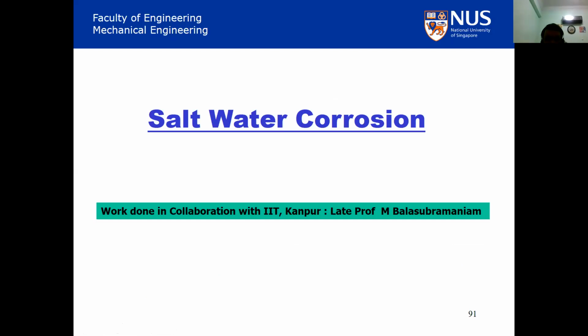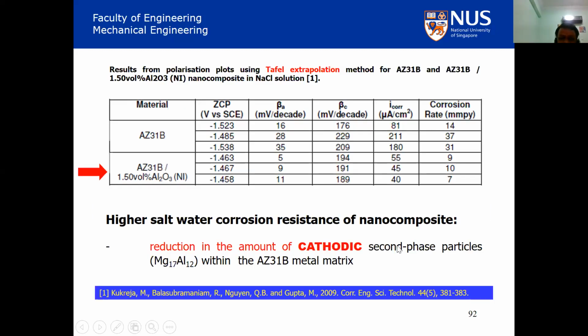We also did the salt water corrosion response of the nanocomposite in collaboration with the late Professor Balasubramaniam from IIT Kanpur. We sent the samples to them, and he found that if you put, for example, 1.5% Al2O3 in commercial alloy AZ31, you almost reduce the corrosion rate to one-third, and he attributed that to the reduction of the cathodic phases in the microstructure. So if you reduce the number of cathodic phases in the microstructure, the rate of corrosion goes down.